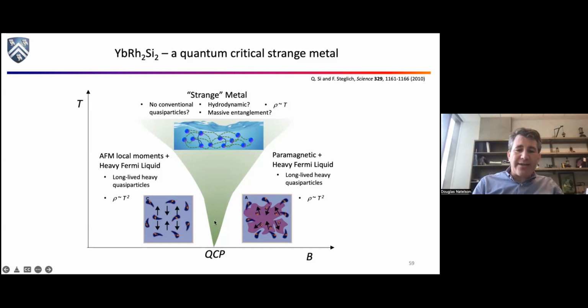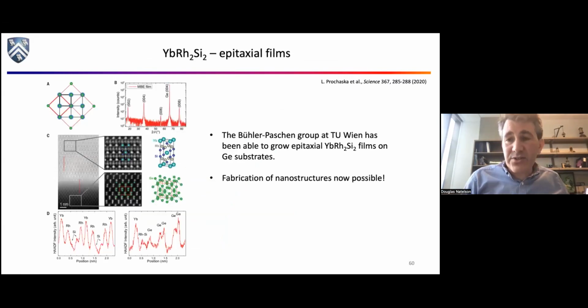I should point out, I showed this thing spreading out in magnetic field as you go up in temperature. All of this excitement is happening below about 0.3 of a degree above absolute zero. So by the time you're up at a couple of Kelvin, where we start doing our measurements, the whole region of magnetic field is this strange metal region in this material, okay? So again, our ability to do this experiment depends critically on the availability of material. And Professor Bühler-Paschen in Vienna is basically the only group in the world that's figured out how to grow nice films of this stuff, as opposed to single crystals that are kind of bulky objects, right?